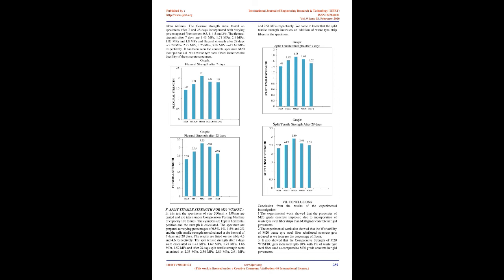Flexural strength was tested after 7 and 28 days with varying fiber content of 0.5%, 1%, 1.5%, and 2%. After 7 days, strengths were 1.43 MPa, 1.71 MPa, 2.1 MPa, 1.83 MPa, and 1.8 MPa. After 28 days, strengths were 2.28 MPa, 2.75 MPa, 3.25 MPa, 3.05 MPa, and 2.62 MPa respectively. This shows that M20 concrete incorporated with waste tire steel fibers increases the ductility of the specimen.